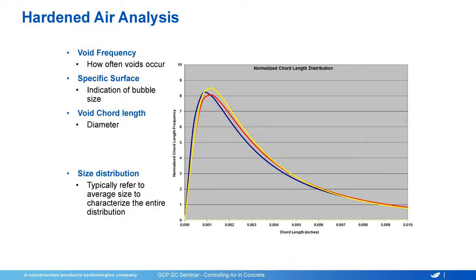Void frequency, that's how often the voids occur. Again, specific surface is the indication of the bubble size, and then the void chord length is the diameter of the bubbles. So here we're just seeing a distribution of those bubbles, and the ones that are down here on the very small end is what we're looking for to get us very good freeze-thaw protection. In reality, we can get over this 0.010 and still have good freeze-thaw protection, but we're going to need more bubbles to do that.